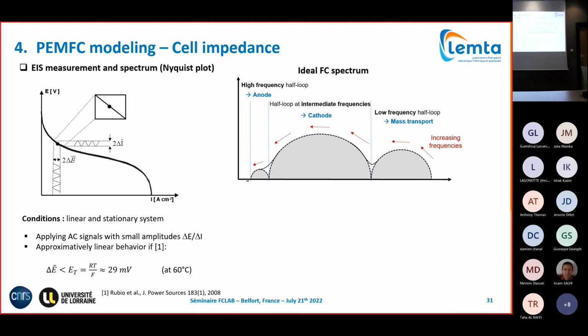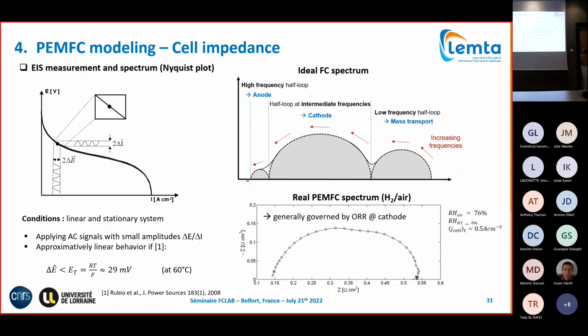And at very low frequencies, we have a third loop associated with mass transport, mostly oxygen, primarily when you feed your fuel cell with air instead of oxygen, since oxygen diffusion is very slow compared to the reaction kinetics. So this will appear at very low frequencies. So that's theory. In reality, most spectra will be composed of two more or less mixed groups. Normally the anode reaction kinetics are negligible compared to the cathode reaction kinetics, and the anode will be neglected or overwhelmed by the cathodic loop, and the separation between the cathodic and mass transport loops is more or less pronounced.